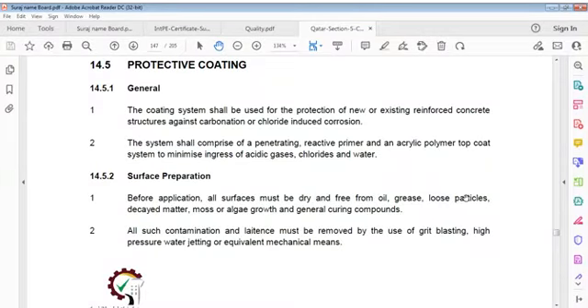A coating system shall be used for protection of new or existing reinforced concrete structures against carbonation or chloride induced corrosion. The system shall comprise a penetrating reactive primer and an acrylic polymer top coat system to minimize ingress of acidic gases, chlorides, and water. And in surface preparation, before application, all surfaces must be dry and free from oil, grease, loose particles,